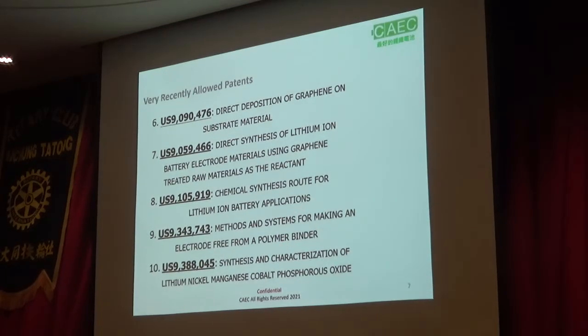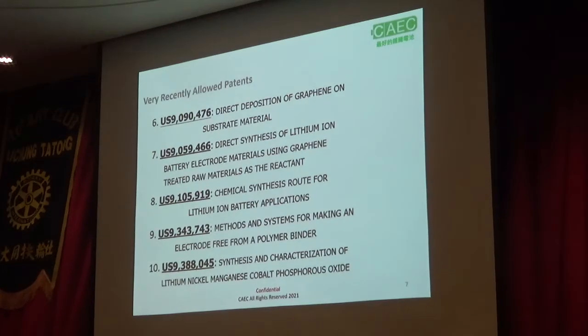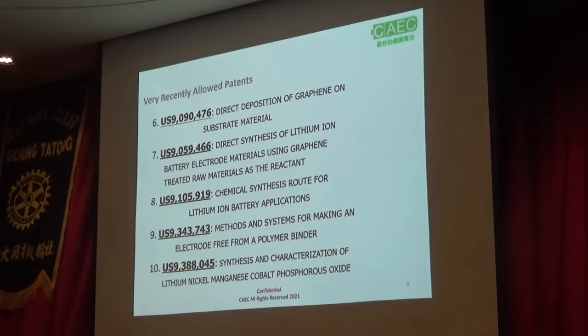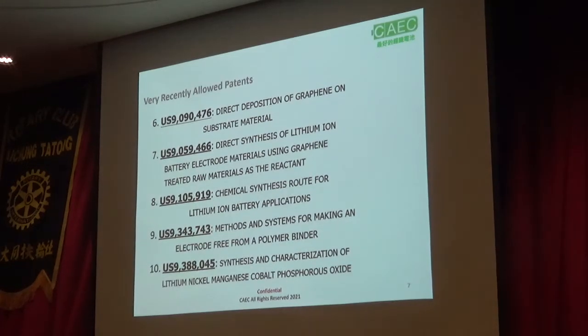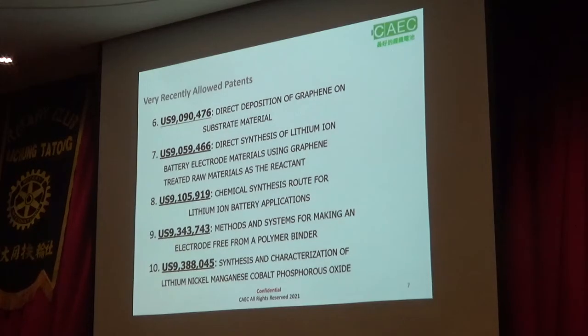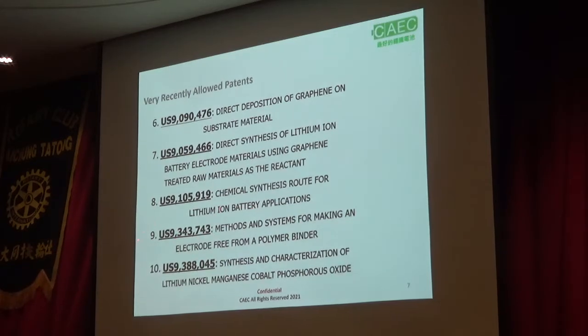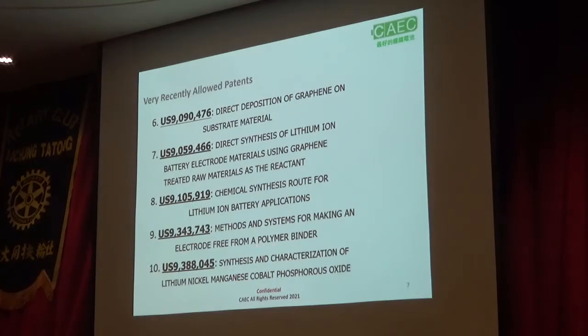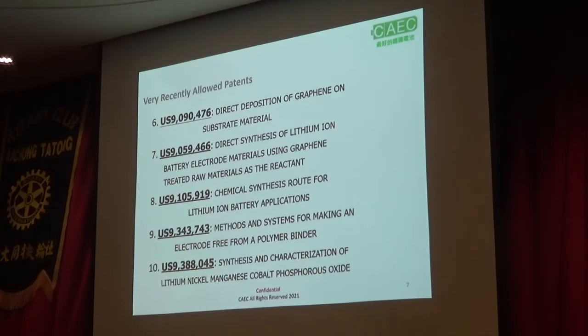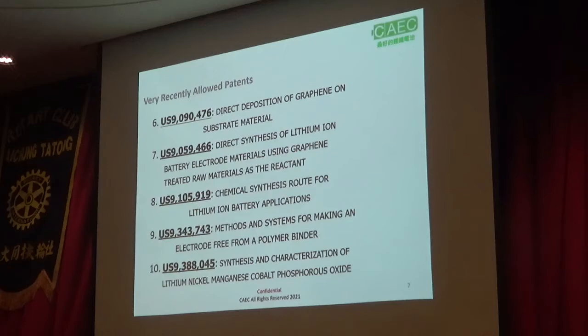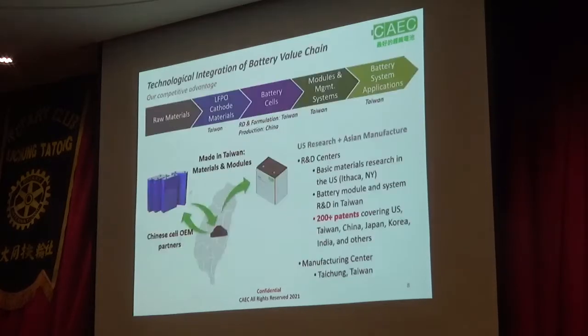Normally, we make the electrode using polymer binders and make a slurry and do the casting on the substrate. And then do the drying, calendering, and then the rolling to make it a jelly roll or stacking. But in this patent we show how to avoid using polymer binders. That means we use dry methods in preparing the electrode. And then the very last one shown here is the characterization of this lithium nickel manganese cobalt phosphorus oxide. This is a high capacity material. It's about double the capacity of this iron-based material. So that's the next generation material.